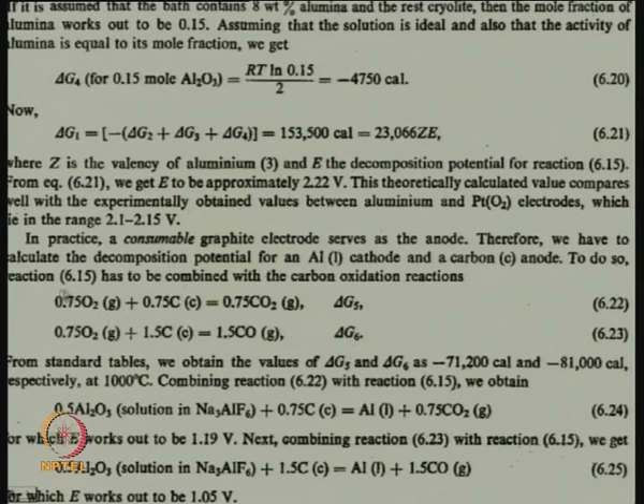To do so, this reaction 6.15 that I had shown earlier has to be combined with carbon oxidation reactions: 0.75 O2 plus 0.75 carbon giving you CO2, similarly oxygen reacting with carbon to give CO. Which means now we will get 2 more values, delta G5 and delta G6, which are these values. These will have to be combined with the reaction I had written earlier, and then we get this final reaction.